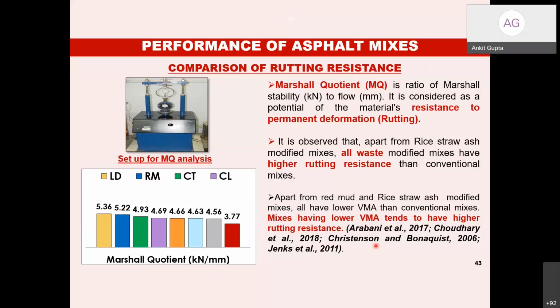It is the ratio of the Marshall stability to the flow values, and this has been widely done by the researchers, widely accepted in the literature. So we have done this kind of Marshall quotient test, and what we could find out is that apart from the rice straw ash, all waste modified mixes have higher rutting resistance than the conventional mixes. The conventional mix was with the stone dust, and with respect to stone dust, all the waste modified mixes have higher rutting resistance.